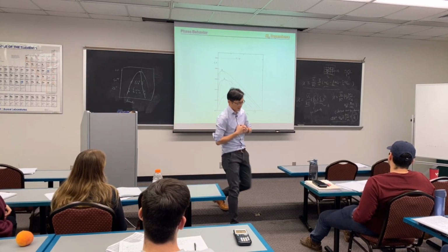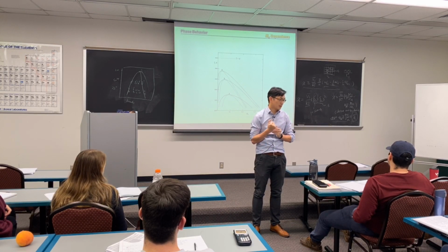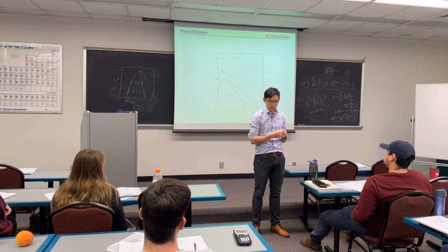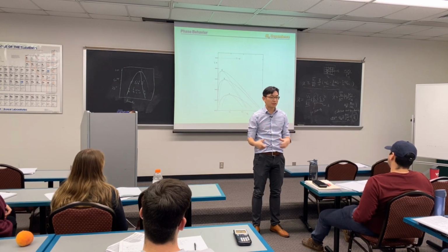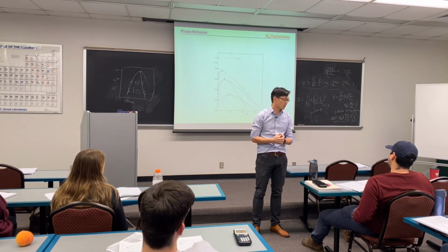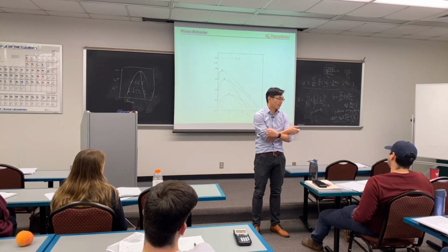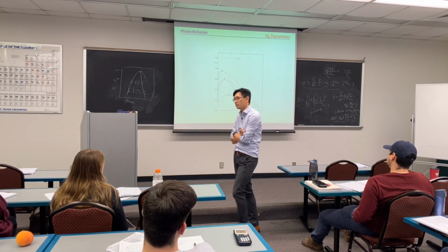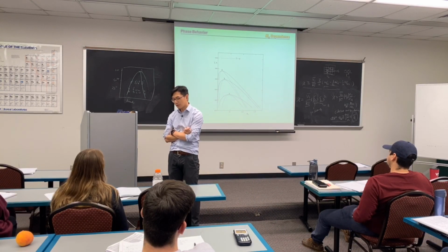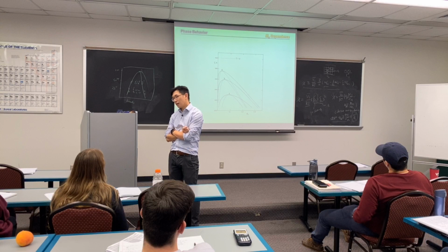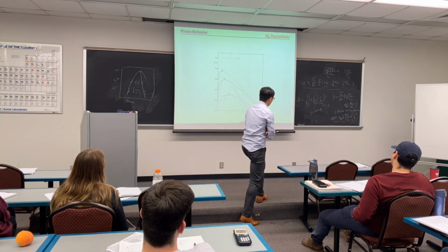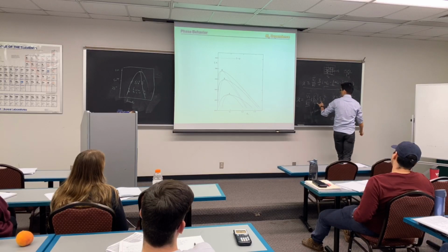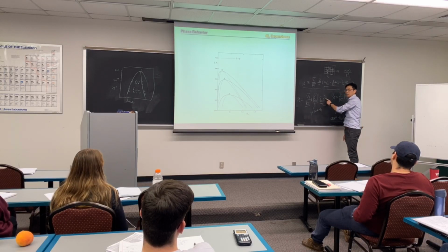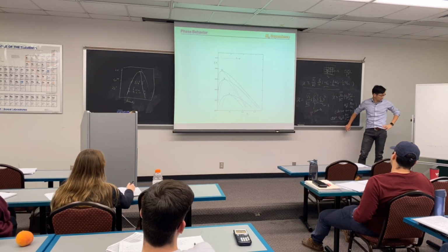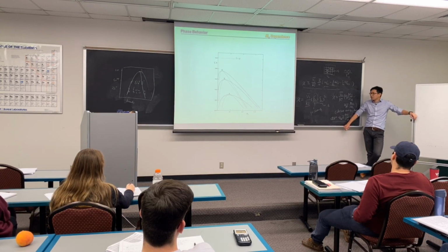Now let's think about one scenario of how we can use it. You know the energy needed to move one toluene all the way to infinity from this room. We also know the energy needed to remove a hexane. Now you can calculate the chi parameter based on what we have discussed. If you know the cohesive energy density for one, and you know the cohesive energy for the second material, it will be the cohesive energy difference squared. That will give you the chi. It is so simple.